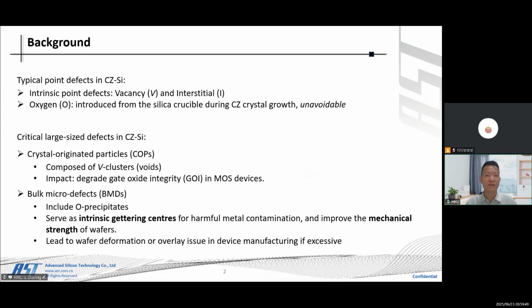In the semiconductor industry, silicon is one of the most important materials, and the control of the defects in silicon wafers is critical. Typically, there are two kinds of point defects in Czochralski silicon materials. Intrinsic point defects, including vacancies and interstitials. Secondly, impurities such as oxygen, which is induced from the silica crucible during the Czochralski crystal growth, is considered unavoidable.